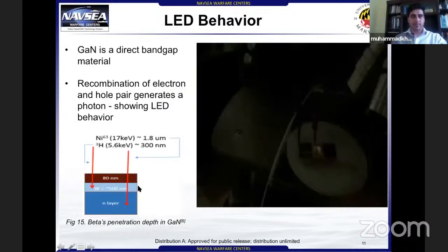Figure 15 here shows the beta's penetration depth in GaN. As you can see here, nickel 63 has 17 keV energy, and it penetrates deep into the N layer. This middle layer is the depletion region. As it penetrates further into the N layer, it creates electron hole pairs that are not collected and do not contribute to the output power. These electron hole pairs simply recombine.